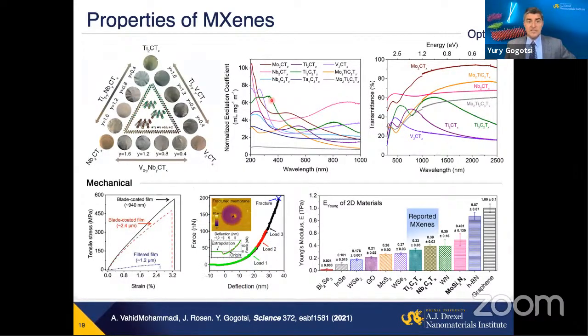And you can see that there are all these absorption peaks, which are plasmon resonances, transverse surface plasmons, which are controlled just by the thickness of this material. So lateral dimensions don't affect the position of those peaks here. And some MXenes are transparent in IR, some absorb strongly in IR. So we have materials with basically a variety of optical properties.